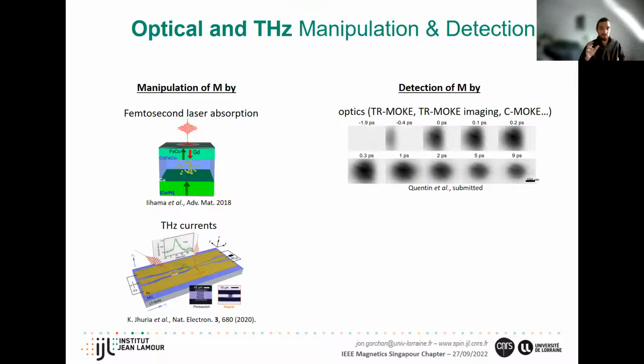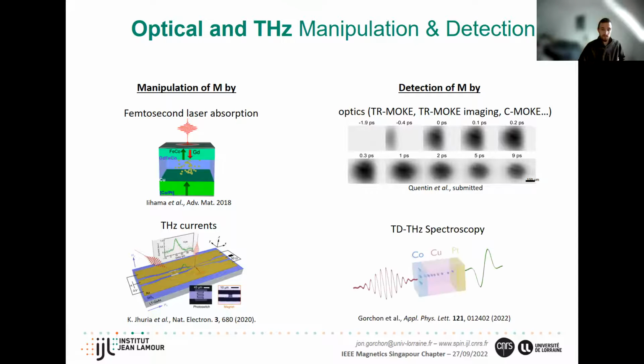By playing with the polarization of the light, you can basically separate different layers in a spin valve, for example. And a new method that we're using more recently to try to characterize the ultrafast dynamics is to use time domain terahertz spectroscopy. Typically we use what we call a spintronic emitter, and this can give you information on the spin transport and fast dynamics.